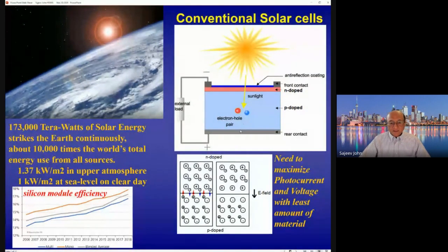This migration is typically assisted by some sort of an electric field that's generated inside the semiconductor, usually caused by doping the crystal with donors and acceptors, so that there's an excess concentration of electrons in one region. Those excess electrons can then diffuse to the other region until an electric field is generated that prevents any further diffusion. And when the electrons and holes are created by absorbing a photon, when they see this electric field, one charge carrier goes in one direction and the other goes in the opposite direction, causing charge carrier separation and preventing the likelihood that these electrons and holes would recombine and give away their energy.